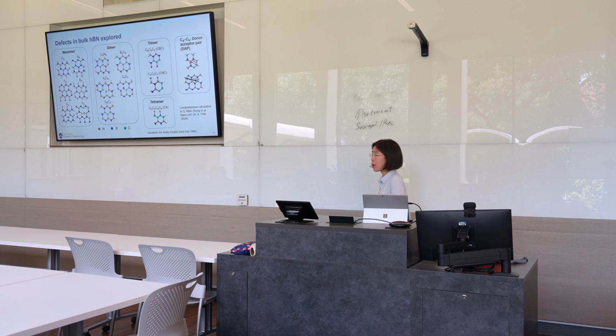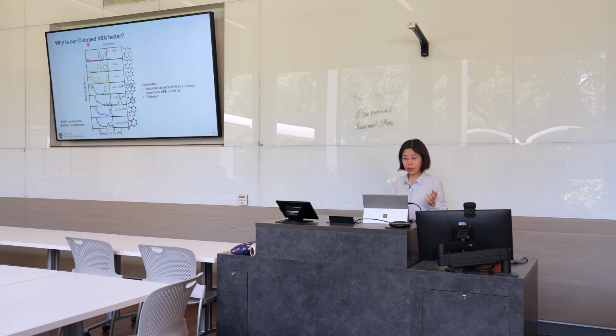I should also mention there is a comprehensive calculation done in monolayer boron nitride, and you can refer to that work. For our work, we looked at bulk boron nitride because our sample is about 30 nanometers thick. So we have many candidates, and we need to first screen them. The first step to screen them is to look at the optical absorption spectra of all of these defects. If these defects have optical absorption close to the experimental value, and if they are polarized, we think they are valid candidates. After looking at all the defect candidates, we have 7 left. You can see in all these cases, there is optical absorption close to the experiment, and they are all polarized. So we still need to screen them. There are still 7 candidates.